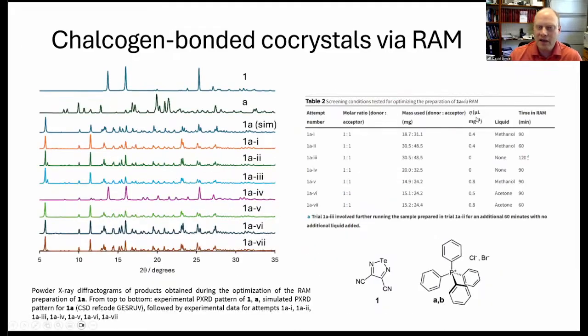When we looked at RAM, though, of the same molecule, you can see on the right here, even after 2 hours, it does not degrade this donor molecule. And so we thought, okay, this is good. Maybe we can do something with RAM with this molecule without it falling apart. Okay, and indeed we were able to do that.